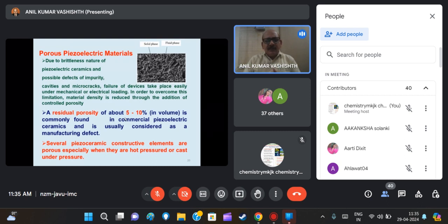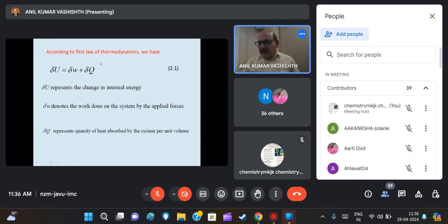Sensor, piezoelectric material. There is a built-in 10% error, which is built into the system because I am neglecting the pore space, and could be the micro cracks also. So here we thought, why should we not give an exact mathematical model for piezoelectric materials when porosity is included? So a class of porous piezoelectric materials was defined, and an attempt was made in 2006 by me and my students to develop a first theoretical framework for porous piezoelectric materials.